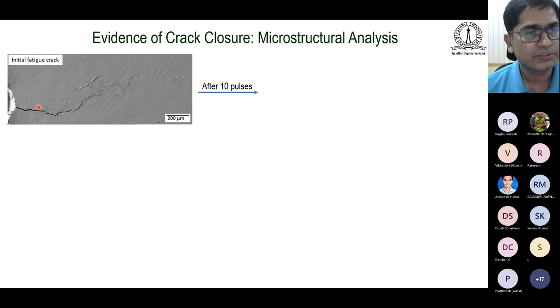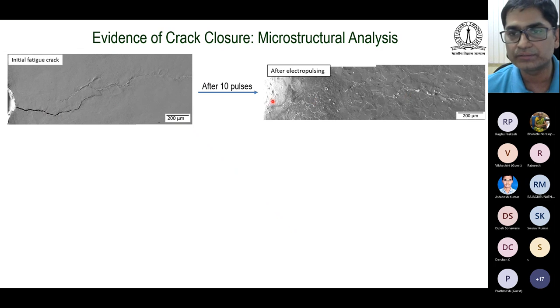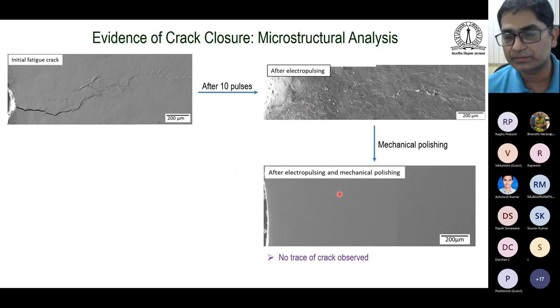So here are some results. This is the initial fatigue crack that you can see here. And then after 10 pulses, the crack gets healed, which is more clear as we do the polishing. After polishing, we can't see any evidence of the crack at all. So the crack is completely gone.